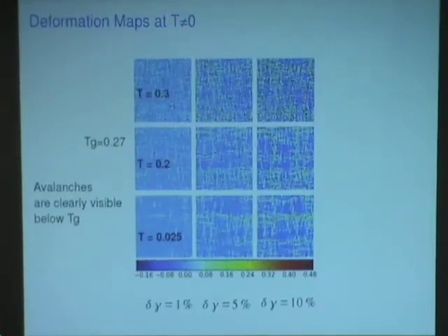Just to follow up on what Craig was saying, what I showed yesterday was that you see spatial correlations only up to the point where you get a total displacement over that region of order a lattice constant or particle diameter. That's completely consistent with the scaling with system size and gives quantitatively the prefactor for the linear scaling with system size.